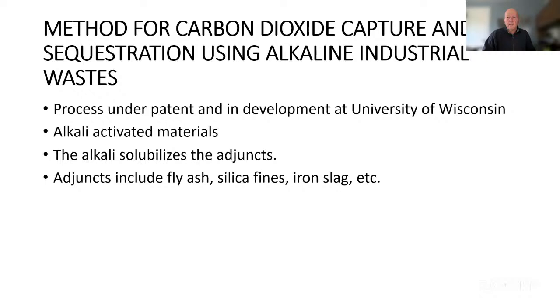They're taking a fly ash pond, that they've ended up talking to, I think, somebody down in Georgia about using their fly ash for whatever reason. And so they're taking that and they are essentially bubbling ambient air through it. It's absorbing the CO2 in the air and carbonating the calcium. And then they add that into the concrete mixture that's being mixed up in a ready mix plant locally.